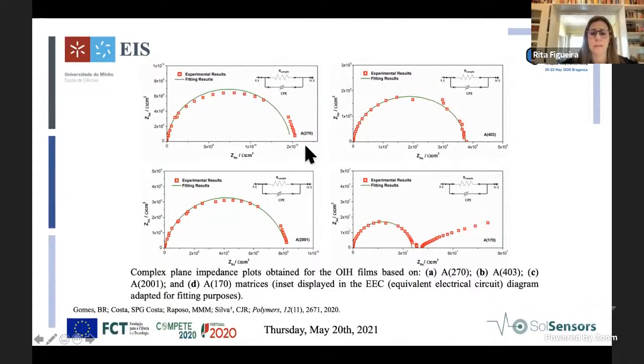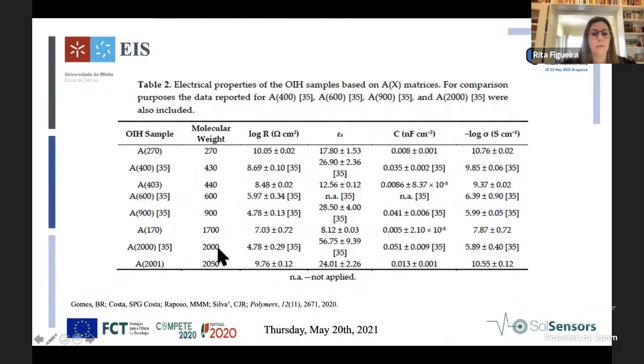So we also studied the samples by electrochemical impedance spectroscopy, and we performed adjustments to the equivalent electrical circuit and made the fitting and obtained the following results. You can see here that generally, as the molecular weight of jeffamine increases, the normalized resistance decreases.